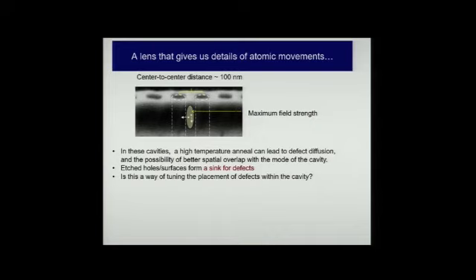It seems here that this exquisite lens has helped us to see not only details of the atomic environment of this defect, but by using the lens while we do something active and dynamic to the material, it seems that what may be happening is that these defects, and this is the sort of high field region, may be given thermal energy, enough thermal energy to diffuse. Where do they diffuse? Actually, Roderick has been helping us with understanding that. It could be random. In fact, there is a direction to it.